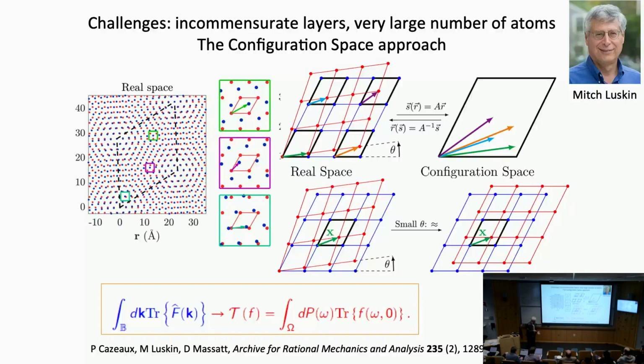Well, in these types of situations, the atomic structure involves thousands of atoms, so it's very hard to do calculations from the DFT perspective. And working together with the group of Mitch Luskin, a mathematician at the University of Minnesota, and his collaborators, we came up with this new way of looking at the system. So basically, you look at all the local environments. We refer to this as the configuration space approach. So in this region, you have this local environment between blue and red atoms. In this region, a slightly different set of local environments. In this region, a different set of local environments.